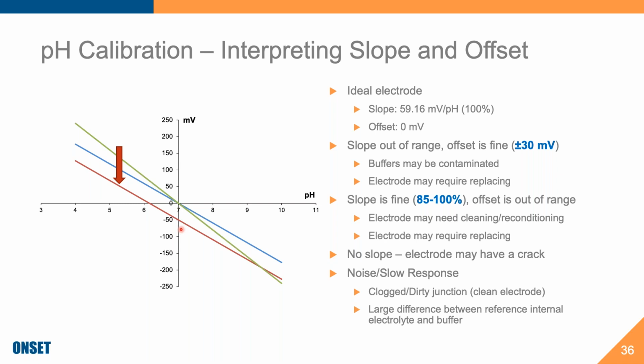If you have noise or a slow response, then it's probable that your junction is dirty. And so now we're going back to the bulb dynamics that I discussed, the potentials. Your bulb has the 3 layers, including the 2 hydrated layers. And if those are affected in any way, you'll have poor readings during calibration. And if you have any cracks, or if it's dirty, or if your junction is dirty, you're going to have slow readings, slow responses. And for those people who are logging pH, you want an electrode that is clean, especially the junction, because if you're logging every minute, for instance, which would be somewhat excessive, your response time might be longer than that minute. So making sure that electrode stays clean is rather important.